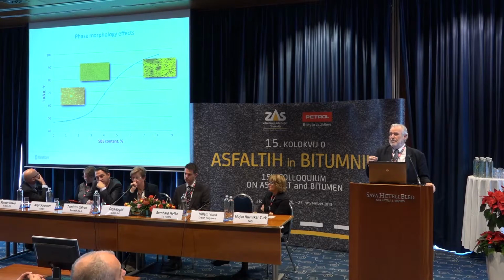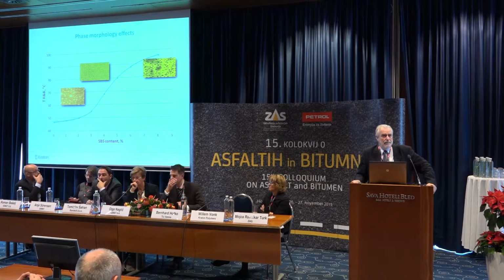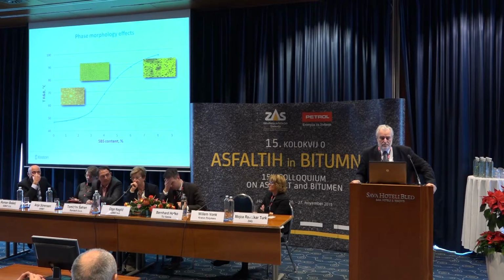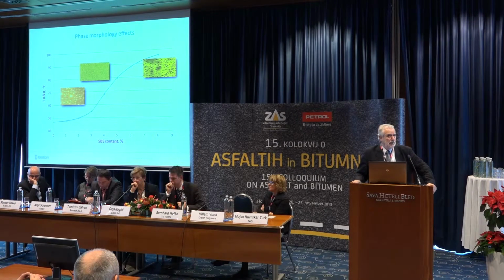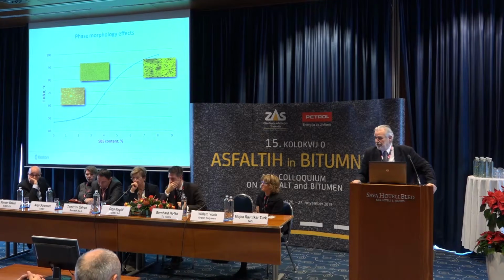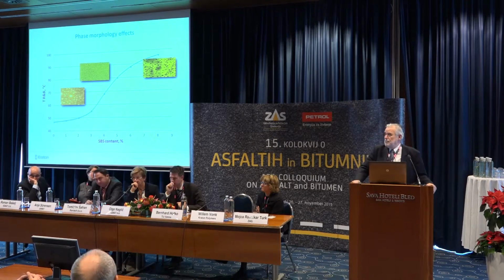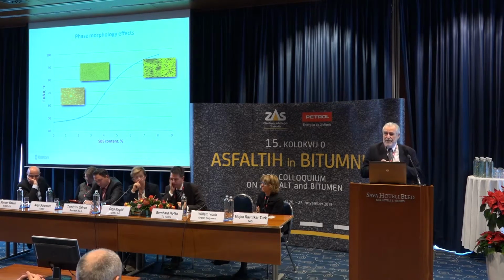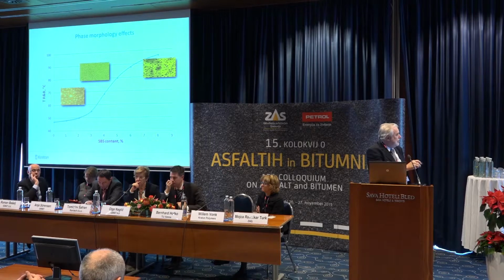Now, why do we believe that we do not get the full potential? This is a curve that has been shown many times. It's about, as an example, the softening point. If you increase the SBS content, you get an S-curve relationship. At lower concentrations, there is not really an increase in softening point. And then at concentrations above 6%, 7%, the softening point also levels off. But there is a significant change in the morphology. It goes from a polymer discontinuous morphology, through a bicontinuous morphology, to a morphology where the polymer-rich phase is continuous.